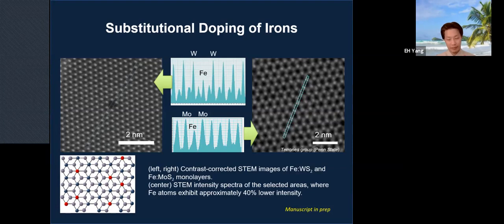So there are several characterizations we put together here, but we show only one here. We use the contrast-corrected STEM images of iron-doped molybdenum as well as tungsten sulfide monolayers. Actually, the left side is the tungsten, the right side is molybdenum sulfide, okay? Now, in the center, it shows STEM intensity spectra of the selected areas, where iron atoms exhibit approximately 40% lower intensity than molybdenum. Okay, so in that way, you can confirm the substitutional doping here.